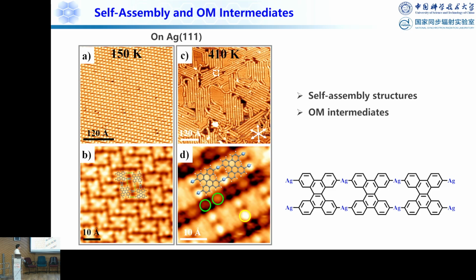This is well known, I think, in the on-surface synthesis community. And then if you go to 410 Kelvin, you see this forms the ribbon on the surface, and you can see the bright protrusions, which are due to the silver atoms, and the bromine atoms which are detached from the molecule. So the structure is like this, okay?